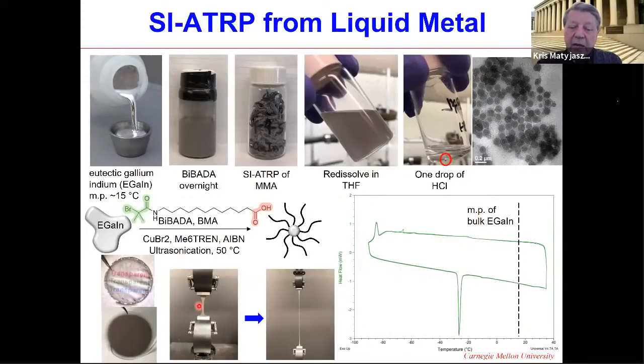I mentioned that they are elastic, very important for soft robotics, and a very intriguing possibility is extending the range of use in temperature, because again it normally crystallizes around plus 15 degrees. In this nanostructured state, you can cool it down to minus 80 degrees, and only then it starts crystallizing. And then it melts at around minus 25 degrees. So you can extend tremendously the useful range of application of these nanomaterials.